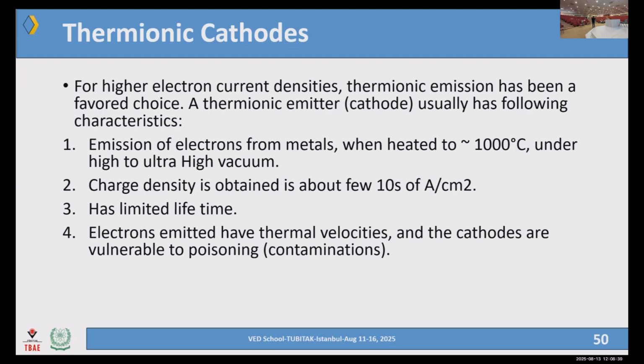cathodes, because the dispenser cathodes are a mix of things. It is just like mixing of materials in order to have higher densities of current at lower temperatures. We mix barium with tungsten to have higher densities at low temperatures. But barium is stored in a reservoir, and that has a limited supply. So of course, but as I mentioned this morning, this lifetime is not that short. The ones which we are using, the manufacturer claims it's around 10,000 working hours if wisely used. Wisely means all the conditions of operation are met. Electrons emitted have thermal velocities, and cathodes are vulnerable to poisoning.